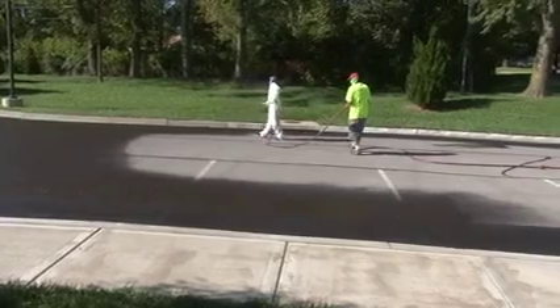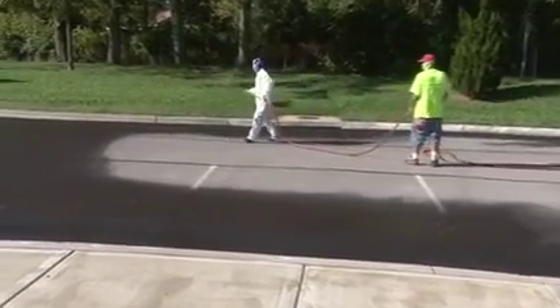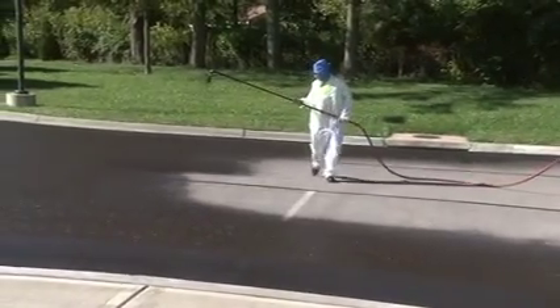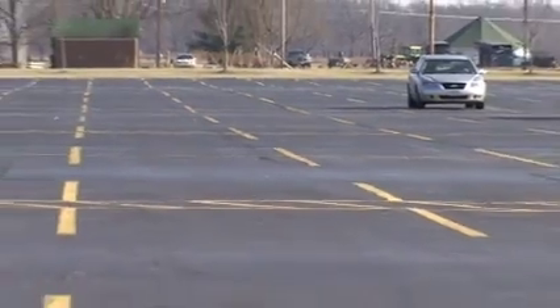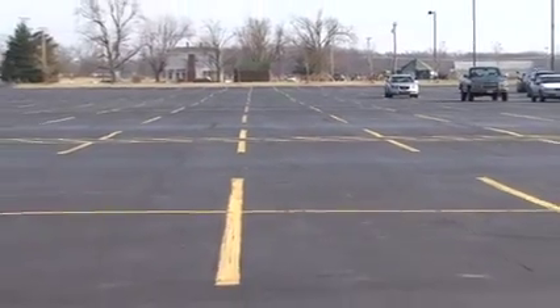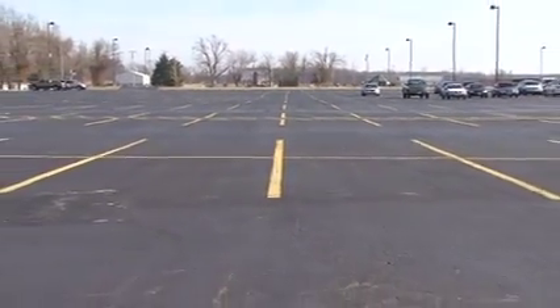When my clients ask me what to do with their new parking lot, my recommendation is after the first year or so that they go ahead and get a good sealant on it, and then stripe it, and then follow that up every 4 to 6 years, depending upon the wear and the traffic, with another coating of it. And if they keep doing that, and particularly dealing with the cracks that will occur with an asphalt parking lot, fill the cracks and seal the lot, it will make that lot last 20 to 30 years. In fact, the lot on one of my properties is now 30 years old, and it's still the original lot. So I can speak very highly of the product and recommend it.